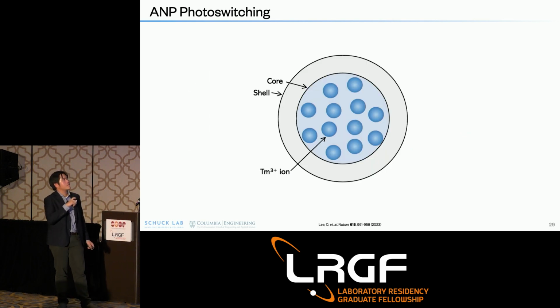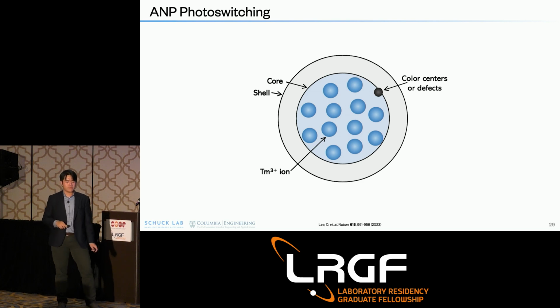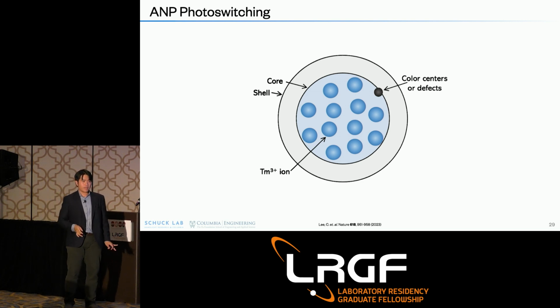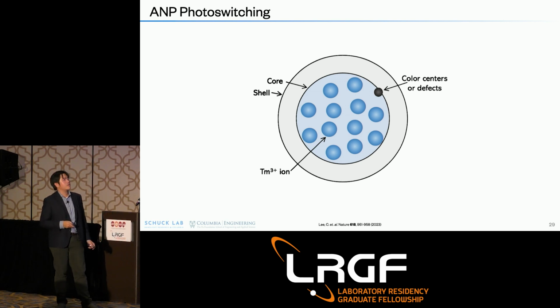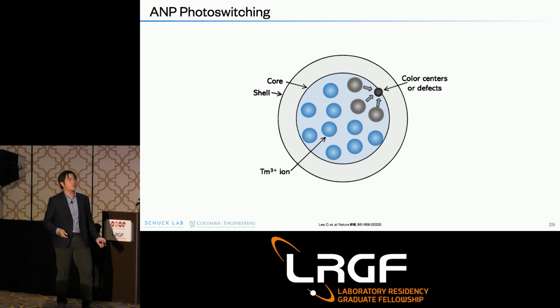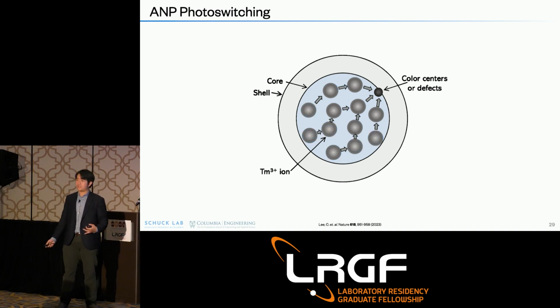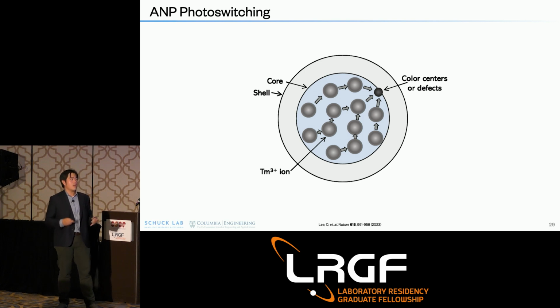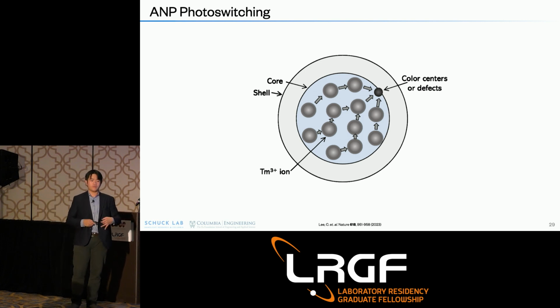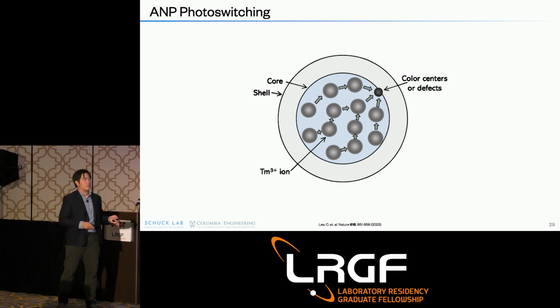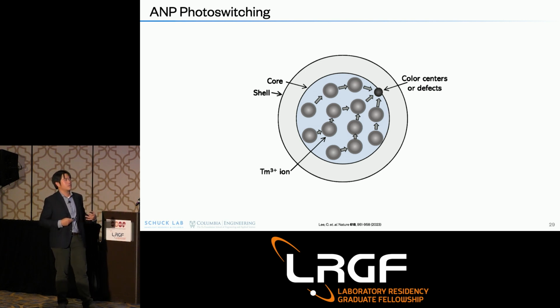So what we think is in this particular case is that when people synthesize these nanoparticles, there's a lot of, I guess, defects that make their way into the core shell interface. And this core shell interface, I think, is what exactly is going on. The color center or defects is in fact quenching a lot of the emission from the lanthanide ions. But because the ANPs, as I mentioned, are really sensitive, the fact that even small defects can start to quench large amounts of emissions means that these nanoparticles are very sensitive to any kind of defects at the center as well. So this is one of the hypotheses we think is responsible for the photo switching effect we're seeing.